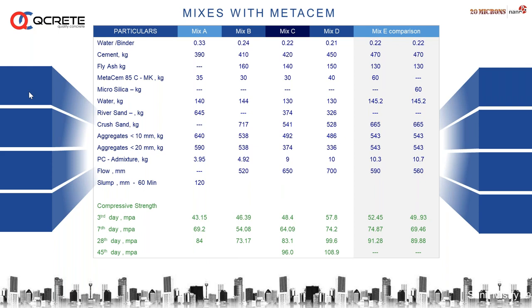You can see the slump part also, where we added PC admixture of 3.95, about 4 kg here. In the second mix, we kept a lower water cement ratio of 0.24 and used cement of 410, a flow concrete with fly ash of 160 and 30 kg of metakaolin. We control the flow of this concrete at 500-550, which is achievable by using 5 kg of PC admixture, 4.92 rather. On the strength part, on the third day we achieve 46-47 MPa, and on 28 days more than 70-73 is achievable.